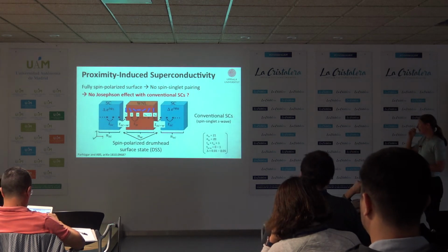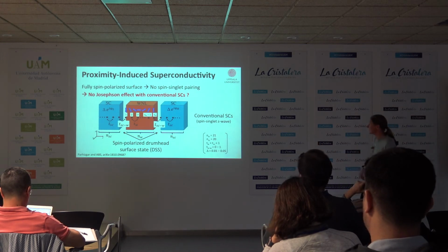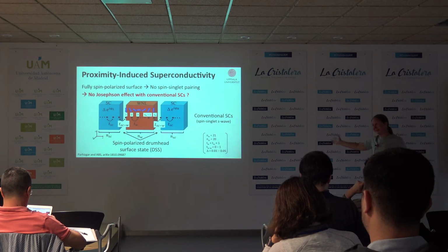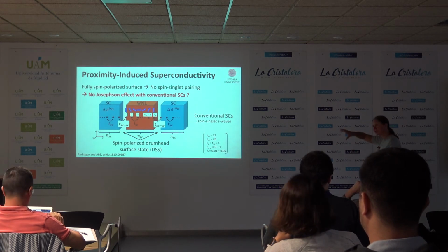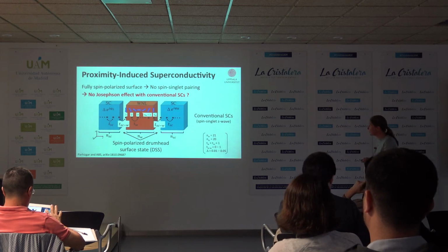So we say, okay, well, we think there's this thing called odd-frequency superconductivity. Can that help us? So we modeled this system. We took our nodal loop material, put it next to two superconductors, and we solved this in a big lattice, essentially. And these arrows here just indicate how the spin winds through the structure. The spin polarized here winds through the spin-orbit coupling, and comes out spin polarized on the other surface.